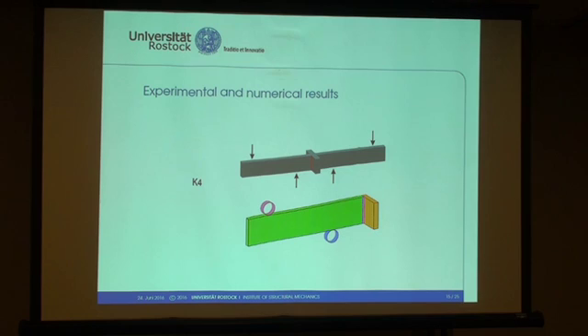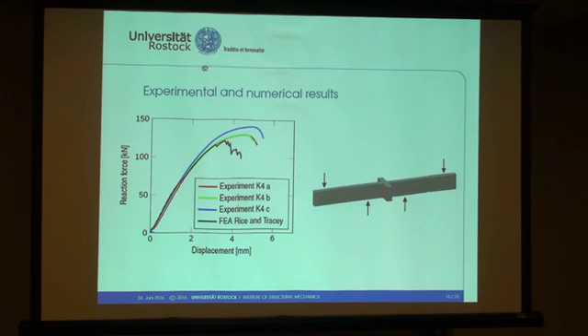Now I want to compare some experimental and numerical results, and I'm going to show you results from K4 under 4 point bending under a constant moment. You can see in red, green, and blue the force displacement curves of the experiment, and in black the finite element analysis using the Rice and Tracey failure criterion. And here the force displacement curve is well reproduced up to 3.5 or 3.8 millimeter displacement, and fracture occurs at 4.2 millimeters in the simulation, in the experiment at 5 or 5.2 millimeters.